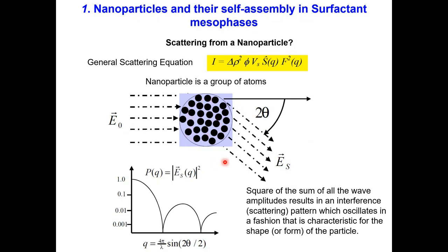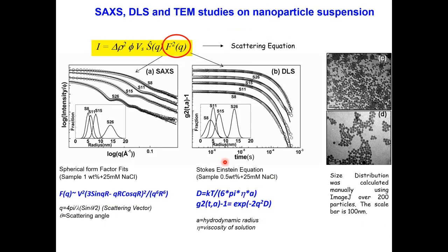Okay. So some time back, I did different types of scattering studies: X-ray scattering, light scattering, and TEM studies on spherical nanoparticles. And you can see that this is the SAXS data, which I can fit to 8 nanometer, 11 nanometer, 15 nanometer, and 26 nanometer particles. But I had also got some information about these particles from dynamic light scattering, in terms of sizes, and also from electron microscopy, which told me that it is a spherical nanoparticle.